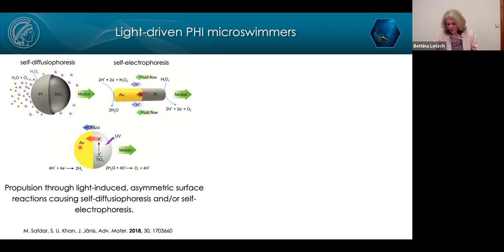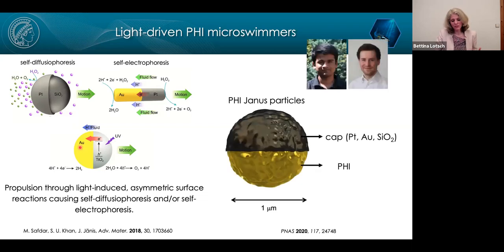And they asked if we, being interested in photocatalysis, have interesting systems for them, and that we would like to study together. And so we said, well, yes, we have PHI, and of course we were intrigued to see if this kind of solar battery type behavior, this charge trapping behavior, would also play out when we use these as microswimmers. And so what we did is we capped these particles. So we made Janus PHI particles. We capped them with a platinum or also gold or silicon dioxide cap. So actually we tried various caps.